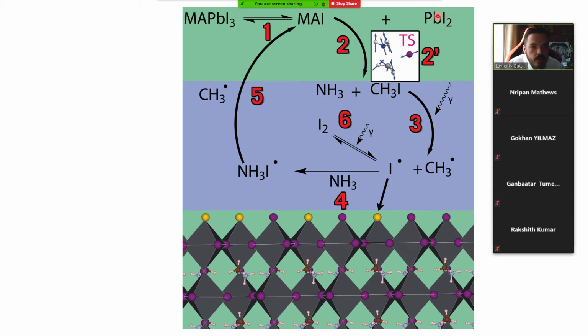So first of all, we segregate into these two phases. We go for a transition state and we get ammonia and methyl iodide. Then our gamma radiation cleaves this methyl iodide further, and we get the iodine radical. Iodine radical can then either passivate the surface, or it can recombine with the ammonia, and then this radical can